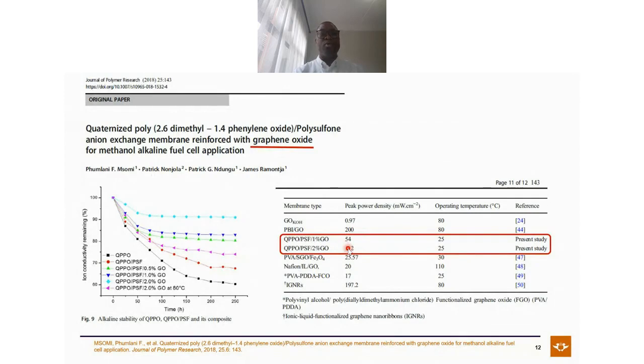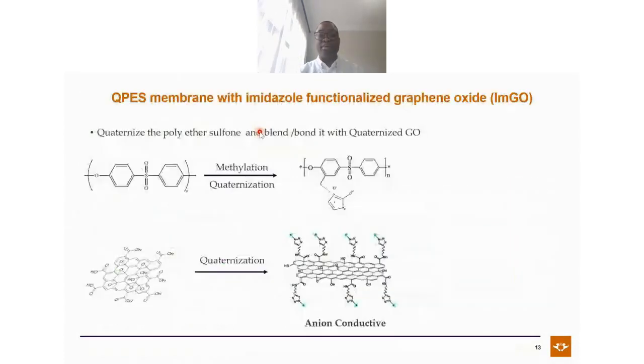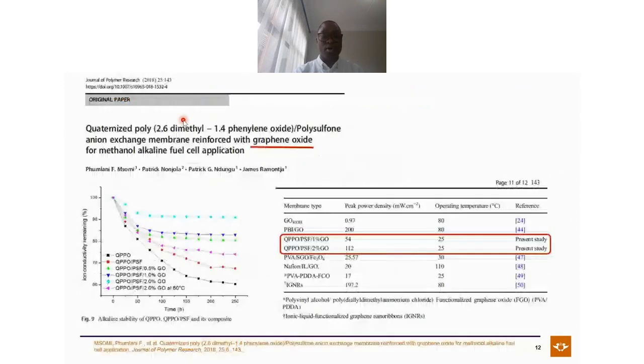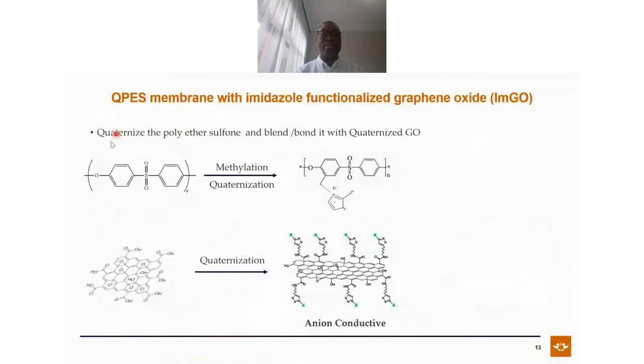So then the question was, what happens if we functionalize the graphene oxide and also put it in the same system? Well, we got a student to do that. This is what they reported. Basically, first of all, this is how they designed it. They were using polysulfone instead of PPO. So they did what we call methylation, and then quaternization. They used imidazole because we've seen that if you have imidazole, it prolongs the lifetime in terms of degradation. They performed this chemistry and were able to get quaternized polysulfone.